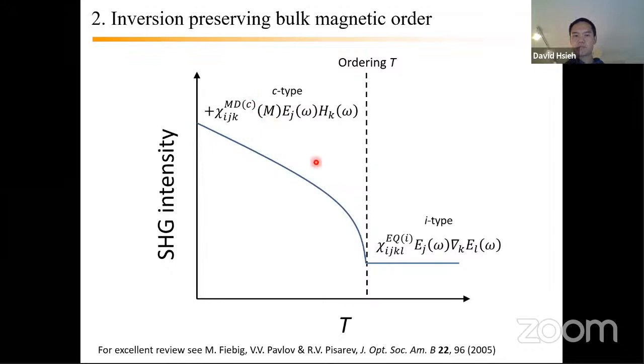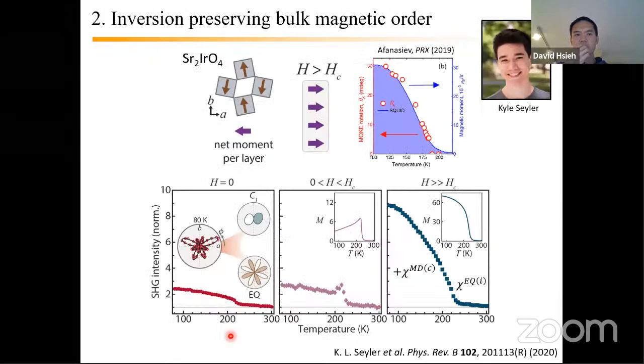And again, there's a great review paper that I invite you to read through if you're interested. And so it turns out that this response is also possible to realize in strontium iridate. If you slap on an in-plane magnetic field above HC, where HC is roughly 0.2 Tesla, then you actually undergo a metamagnetic transition from left, left, right, right to up, up, up, up. And so the system now has a net bulk magnetization.